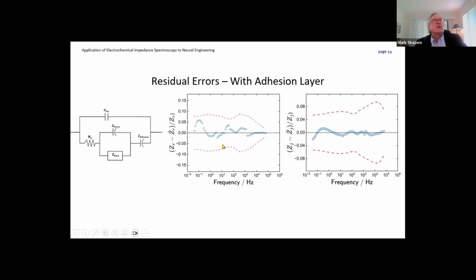If I look at the model with adhesion layer, what we're seeing is that we are getting a much better quality fit. We're seeing little jumps over here. These are artifacts in the measurement. We cannot do anything about that. But we're seeing that the adhesion layer does give us a much better fit to the data.